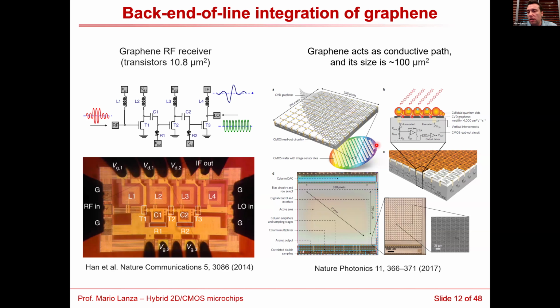This is another study, quite similar. They also transfer monolayer graphene on a CMOS readout circuit. And in this case, it is used as a conductive path with this S shape in a circuit for an optoelectronic application, for a camera. And here the graphene covers an area of 100 micrometers square. In the previous example, the channel of the transistor is 10.8 micrometers square. In both cases, it worked well. However, this is low integration density. These are not very small devices, they are big devices.